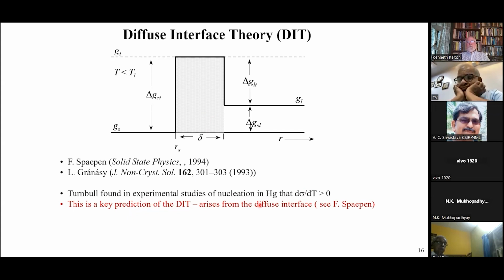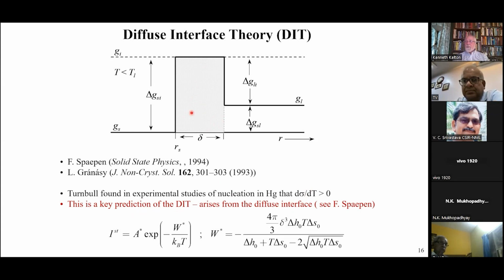This arises because of the presence of a diffuse interface. Turnbull called it a neg entropy effect, where you were overcompensating for the entropy change, and that's effectively what the diffuse interface tells you. If you wanted to do experiments or analyze experimental data with this, you can do it because they've developed an expression, primarily due to Laszlo Granasy, for W star.